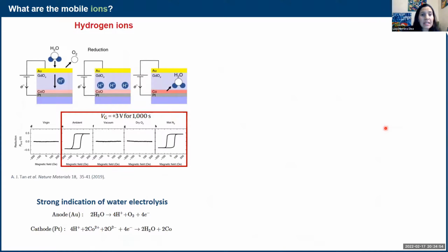And of course, that's not all. There are other ions that could be used for magnetoionics. People have shown already that a mechanism could be seen where the mobile ions are hydrogen ions, or protons, basically. This is the same diagram, from the same group that did the gadolinium oxide measurements that I showed you before. Here they could block the oxygen mechanism by adding an extra layer on top of the cobalt. But by doing this, they could see another mechanism that is driven by the motion of hydrogen.